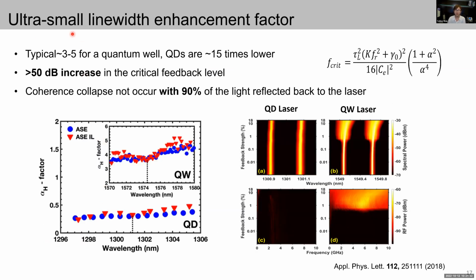For the first, the ultra small linewidth enhancement factor. This value for quantum wells is typically 3 to 5, but for quantum dots it is 15 times smaller. From this scaling factor, the critical optical feedback level for coherence collapse is closely related to this alpha factor, and a quantum dot exhibits over 50 dB increase in this value compared to quantum wells. So when 90% of light is reflected back to the laser, the quantum dot doesn't have any coherence collapse, as evident from this optical spectrum.